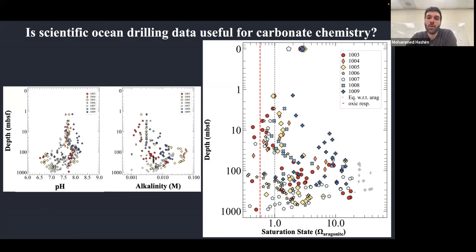And even though there is a lot of scatter in the data, there are really two important trends to observe here. One is this decreasing trend going from supersaturated bottom water. This is 0, meaning that this is the sediment water interface, and this is depth in meters, and going to undersaturation. So there's this interval of undersaturated pore water, and then supersaturation with depth.